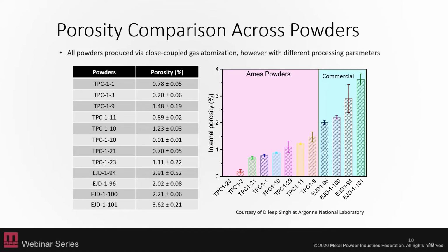All of these powders were produced via close coupled gas atomization. However, the different processing parameters, even using the same exact atomization system, can cause a wide variation in the internal porosity. Again, this is volume of internal porosity versus total volume of powder. So even within our own system at Ames Laboratory, we were able to get close to 0%, but then as high as about 1.5% of internal porosity. And then even amongst the commercial, again, going from about 2% up to 4%. So those internal porosity measurements can also potentially be critical to your process, or to maybe even advertising your powders for a potential customer, and being able to characterize your powders as having lower porosity and then resulting in a higher AM build quality.